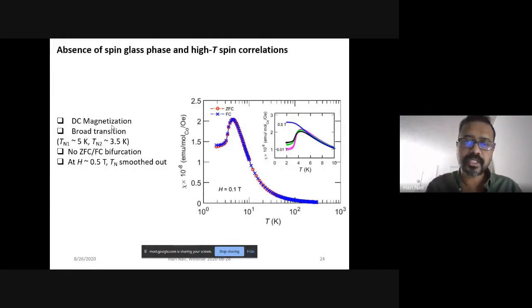Now, once the structure is determined, we want to know what kind of magnetic properties it exhibits. So the best way is to measure the magnetic susceptibility as a function of temperature. And that's the plot that you see now. The magnetic susceptibility increases as temperature is reduced. It goes through a broad maximum, and then it decreases again. Now, we cannot say much from this about what type of magnetic ordering or magnetic ground state it might form, but we can say that it's not a sharp transition. It's a broad transition. And most of the time, a broad transition would indicate some sort of disordered ground state.